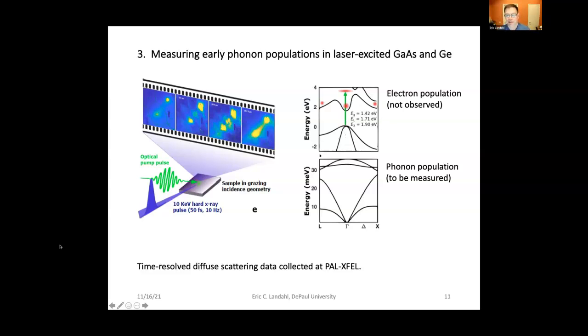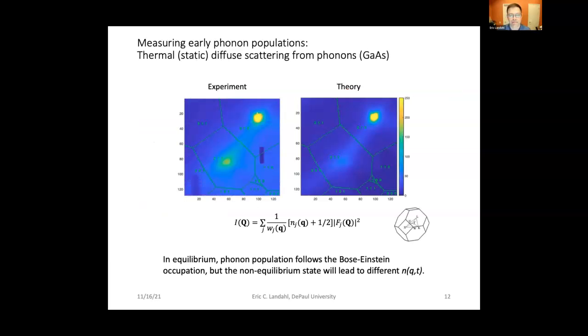I presume that here in the energy band level for the electrons, depending on the excitation energy, shown in green, you're going to populate to different amounts various different electron valleys after some electron thermalization. And then the big question, and all we can measure, is actually where they go when they become phonons. So we don't measure the electrons directly, just like the other experiments, but only where they couple to phonons. And this data was collected at the Pohang Accelerator Laboratory, XFEL, in South Korea. We were very happy to be the first international users there when they turned on a couple of years ago.